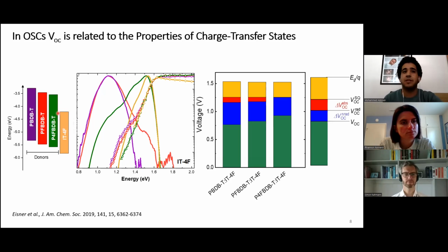So here the acceptor has the lowest band gap. The band gap will not be affected, but we're just changing the energy offset between the two HOMO levels, or mainly the energy offset between this CT state and LE state. What we see is that by doing so, the luminescence is going to be blue shifted to higher energy.